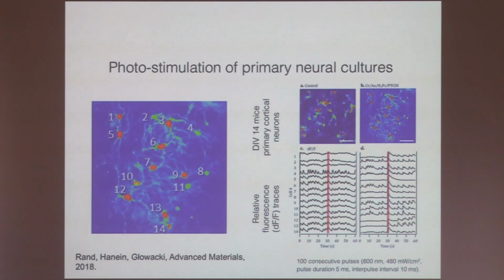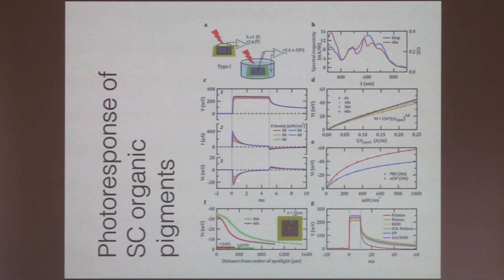Just to emphasize something that I neglected to emphasize before, generally when we measure directly the current going through the electrode, we see that we have something which is capacitive in nature. So this is not direct current. If in this measurement you see something that looks like direct current, then you know for sure that this is not going to be a capacitive process. The fact that we see here something which is capacitive-like doesn't necessarily imply that it's strictly capacitive, because it may still involve very strong Faradaic processes.